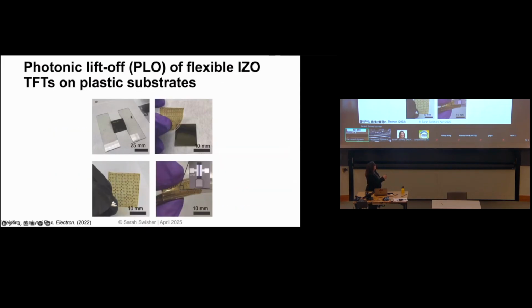So this is a picture of the liftoff process. We actually suspend it above the processing platen with these glass slides, and you can see how easily this peels off. It just peels off right by hand. There's no pulling, and what that means is that there's no residual stress in the film, so it doesn't curl up in a taco, which is really nice. And then the resulting devices are completely flexible. So here's that same transistor being rolled around a small glass rod.